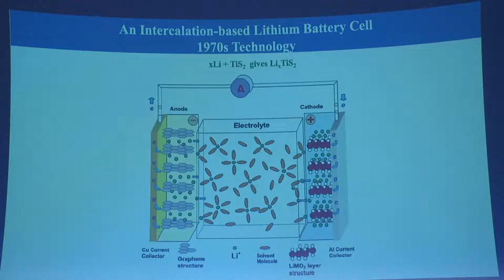So the anode, today we use graphite, and I show you graphite here, the sheets of graphite with little green atoms in between them. On the right-hand side, another layered structure, and I'll show you some examples of that in a moment. But again, we have both layered structures, then in between we have an organic solvent with a salt in it. Typically this is LiPF6, although some of the latest ones are using LiFSI as the salt. It is the solvent that burns. Once that starts burning, then the graphite starts burning. What can initiate it are the oxides, and I'll get into why they initiate it in a moment.